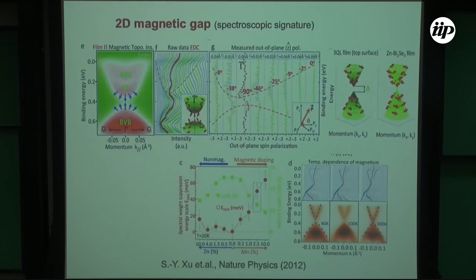Okay, so what we found is that the best way to see whether time reversal symmetry is broken or not is to look at the spin texture of the surface state. Even though the existence of a clean gap may not be clear, if it is due to broken time reversal, then your spin texture will also reflect that. It will not obey time reversal. In the Dirac cone case I showed yesterday, this spin texture is time reversal invariant. K plus, K minus, there is always a relationship between the two.